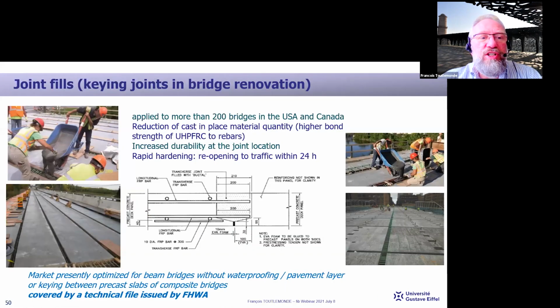So here I briefly mentioned the use of UHPFRC for keying joints between precast elements in the USA and Canada, because this can be an attractive sector, because one of the key advantages is the rapid hardening of the UHPFRC, and the shorter anchorage length of UHPFRC with the rebars, which limits the volume of the joints and makes it possible to reopen to traffic within 1 day, which is much appreciated, especially in zones where the alternative route solutions are not so easy to find.